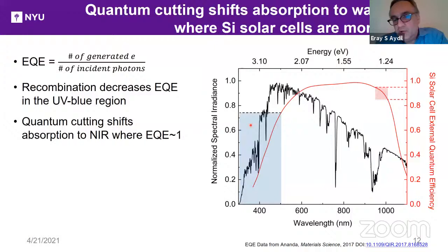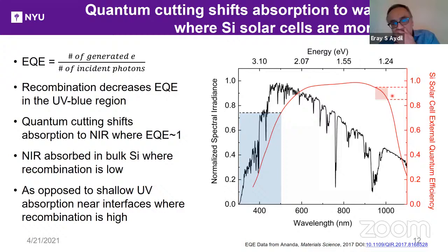So here you see that in the blue, the external quantum efficiency is less than 0.7, much smaller. On the other hand, in the near infrared, quantum efficiencies are much higher, nearing one. And that of course is because near infrared light can go deep into the silicon and be absorbed where recombination is low, whereas ultraviolet and blue are absorbed shallow where there are surfaces and the recombination is high. So quantum cutting, by shifting the blue photons to infrared, also gains in this type of recombination losses. So you not only can increase and surpass the Shockley-Queisser limit, but also come closer to it than had been possible with silicon. So there are two benefits.